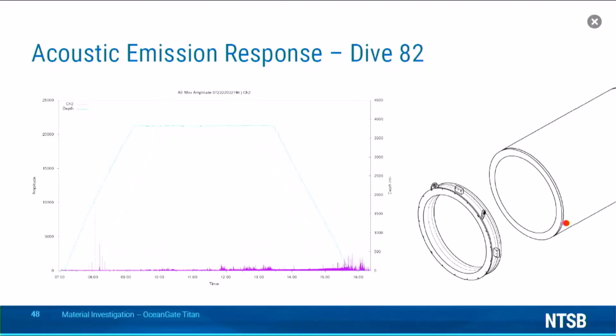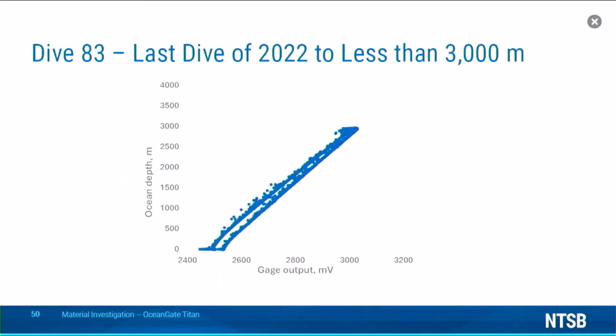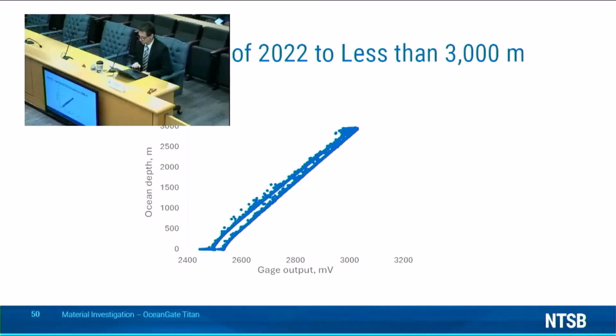Dives 82 and 83 show a trend of the hull becoming quieter with successive dives, as seen here for dive 82. Next slide. And here for dive 83. One note about dive 83: this dive did not take place at the Titanic wreck site and did not go to the same depth as the other dives. According to the dive log, it reached a depth of 2,954 meters. This is the last dive for which acoustic emission and strain data is available.